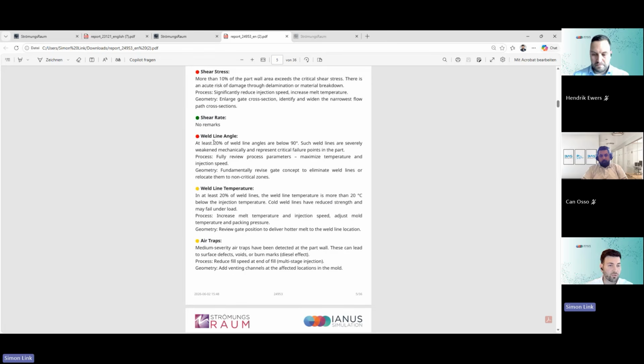And yeah, it says that 20% of the weld lines are below a weld line angle of 90 degrees. So this could be an issue because these weld lines have a weakened mechanical behavior, so they have a lesser strength. And we also have process recommendations here. For example, to make changes to the temperature, maximize it, or also change the injection speed, or for the geometry, we can think about the concept behind our arrangement of the gates to eliminate these weld lines, or also position them in an area that is not that critical.